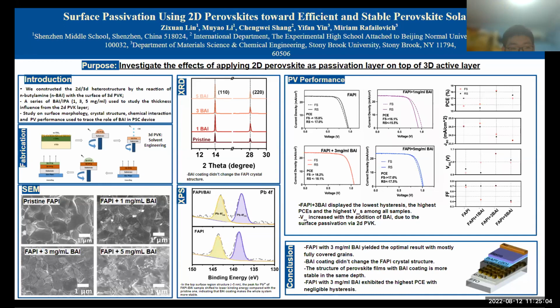Hello everyone, today we will be presenting our project, Surface Passivation using 2D perovskites toward efficient and stable perovskite solar cells. Our goal is to investigate the effects of applying 2D perovskites as a passivation layer on top of a 3D active layer. As a result, we constructed a 2D/3D heterostructure by reacting BAI with the surface of the 3D perovskite layer. We dissolved BAI in IPA at different concentrations to study the influence of the thickness of the 2D perovskite layer on power conversion efficiency. And we investigated the surface morphology, crystal structure, chemical interaction, and PV performance of our device.